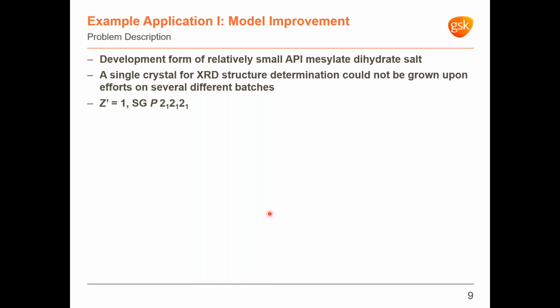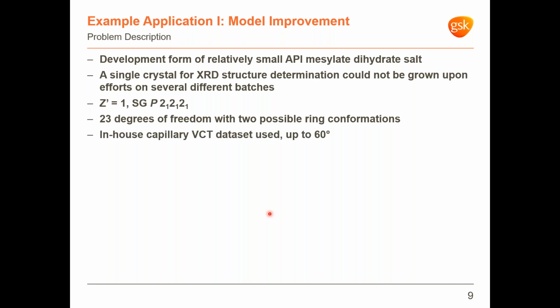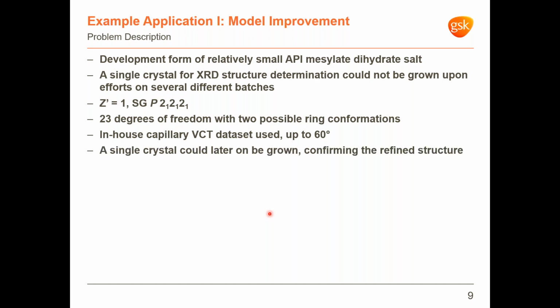Some more information about the problem. XRPD indexing and solid-state NMR were used to define the unit cell and symmetry of the structure, which is orthorhombic in space group P212121 with Z prime 1. The asymmetric unit content presents 23 degrees of freedom combined with 2 possible ring conformations. And XRPD capillary variable counting time data was collected in-house up to an angular resolution of 60 degrees 2 theta. A single crystal could later on be grown from a different batch, as it often happens, which confirmed the accuracy of the refined structure.